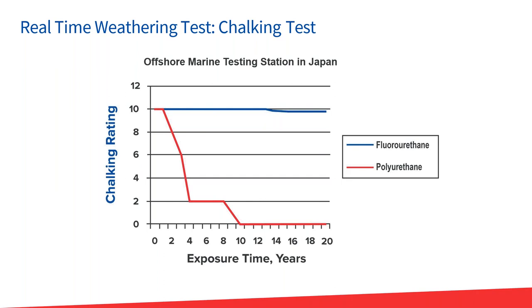So this is a chalking test. It's an ASTM test. And you can see that over close to 20 years of exposure at an offshore marine testing station in Japan, that fluorourethane cross-linked FEVE system has basically the highest chalk rating, close to 10. Some of the areas maybe had a little bit of chalk, but compared to the conventional system, you see a marked difference at only 4 years, and then by 10 years it completely chalked.